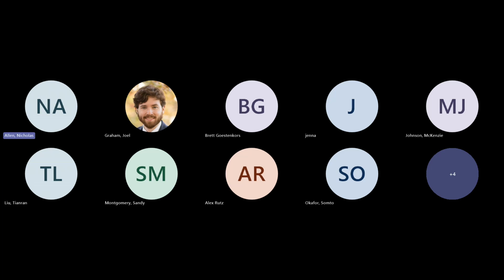30% cytotoxicity is low as a cell person, not ideal. Yep, 70%. I wondered your thoughts on that 30%, and whether the comparison is to cells that weren't in your hydrogel material. Yeah, so when I was looking at the ISO, I was also surprised by the 30% reduction, especially when you're only applying the material to 10% of the monolayer. It's a low percentage, and so to see a 30% reduction.